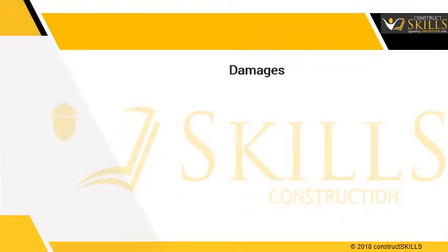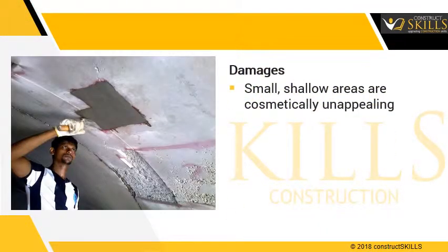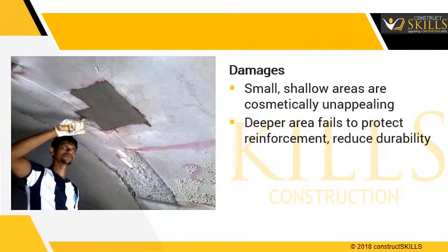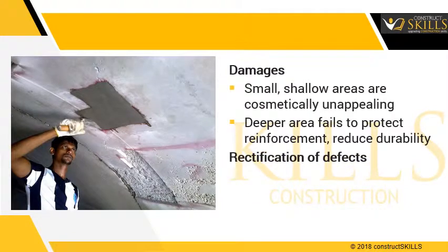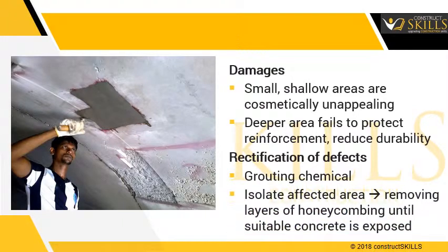The damage can occur as small, shallow areas that are cosmetically unappealing. Deeper areas lead to reduction in protection to the reinforcement, hence possibly durability problems in the future. The possible solution is to apply grouting chemical, or isolate the affected area by removing layers of honeycombing until suitable concrete is exposed.